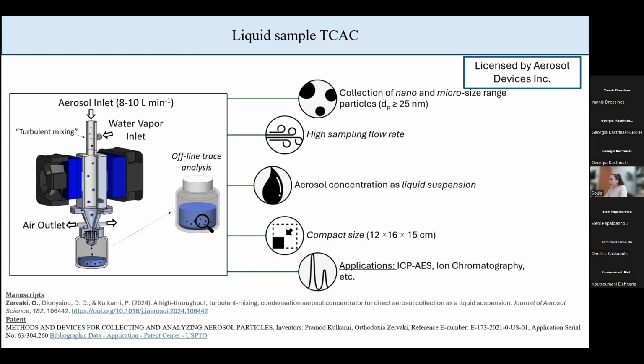And for that reason, because it was getting too complicated, we decided to switch to liquid collection so we can increase the flow rate without having any concerns on that. And this is what we did. We went up to 10 liters per minute collection flow rate, and I increased the size of the mixing section a little bit and the size of the growth tube as well. I also replaced the plastic growth tube that I was using before with an aluminum one. And I put 2 thermoelectric coolers on two opposite sides of the growth tube, so I can cool the whole growth tube, with the aim of enhancing the growth of the droplets.